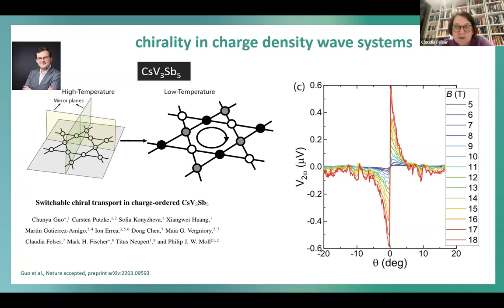This is this famous superconductor where we found the switchable chiral transport. So it has a chiral charge density wave. But again, why didn't people see chiral charge density waves very often? Simply, if you have both domains, you think it's a higher symmetry. So we really have to be more careful when we look into the structure of the materials, okay? So this is, I think, something Christina would fully understand. And the last slide, I hope, comes now.